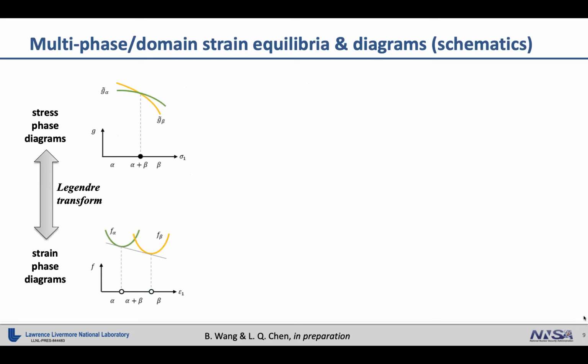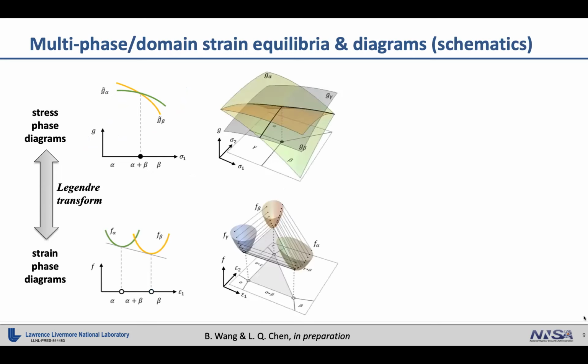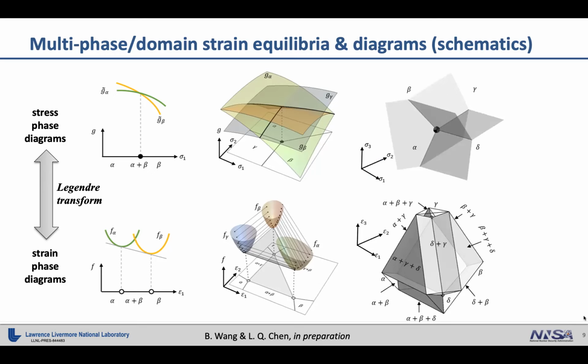And by using this 1D model, by intuition, we can generalize it to 2D, in which case there are 3 phases coexisting and a triple point in the stress phase diagram constructed by the Gibbs free energy surfaces. While for the Helmholtz free energy in terms of the strain, we can have this triangular region, which represents the 3-phase region in the strain phase diagram. We can even generalize it to higher dimensions, although it's a little bit challenging to visualize higher dimensional free energy surfaces. But for the phase diagrams, by intuition, we can get some notion of how they would look topologically.